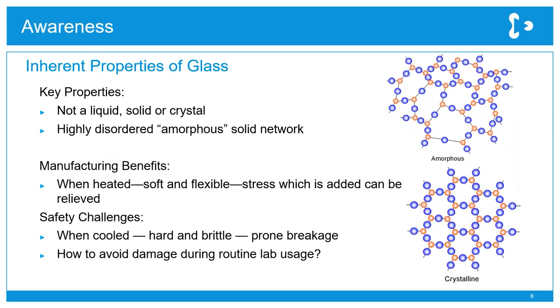So glass is not a liquid, a solid or crystal, so it's usually described as amorphous. And this structure makes it quite brittle. And because glass doesn't contain planes of atoms that can slip past each other, there's no way to relieve stress. And so when excess stress forms, this forms cracks. And at that point, there's a surface flaw. So glass can be extremely fragile.